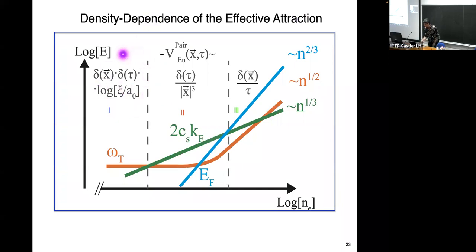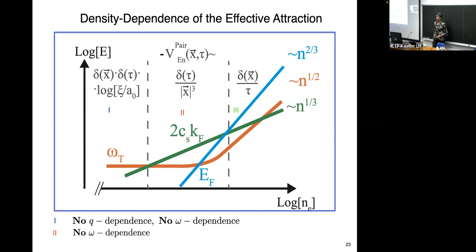Here we have completely local. Here we have local in time, but power law in space. And here we didn't discuss this case, but we would have local in space and power law in time. So in the first regime here, there's no Q dependence, no omega dependence. Second regime, we have no omega dependence. And third regime, we have no Q dependence.